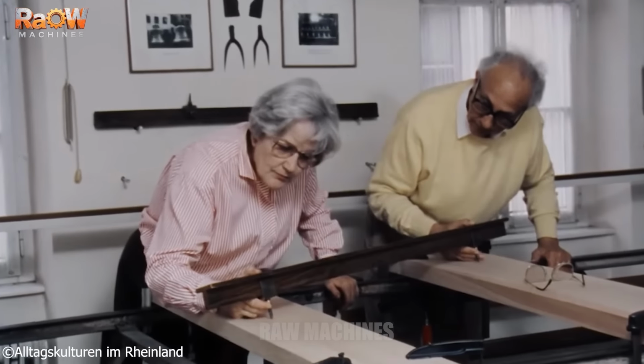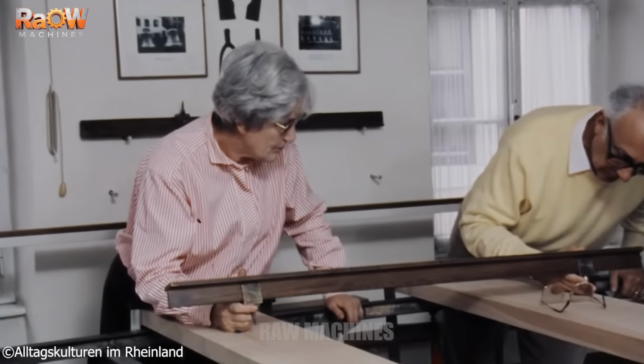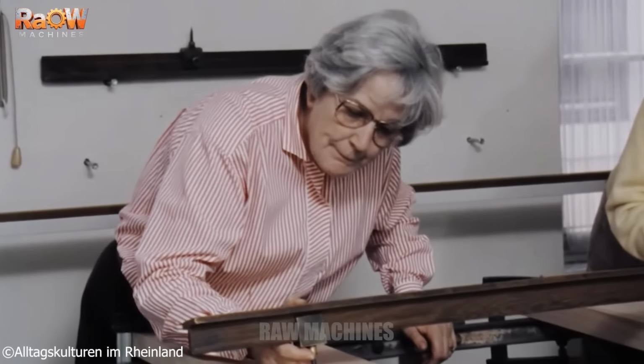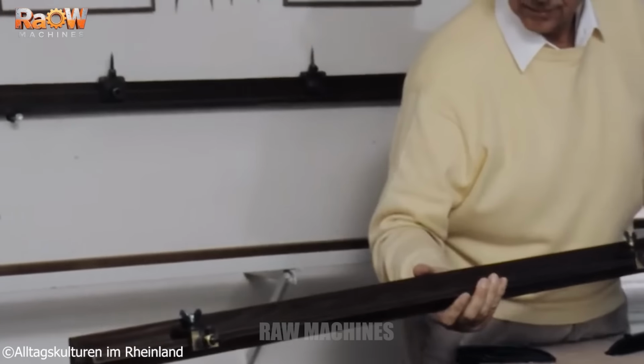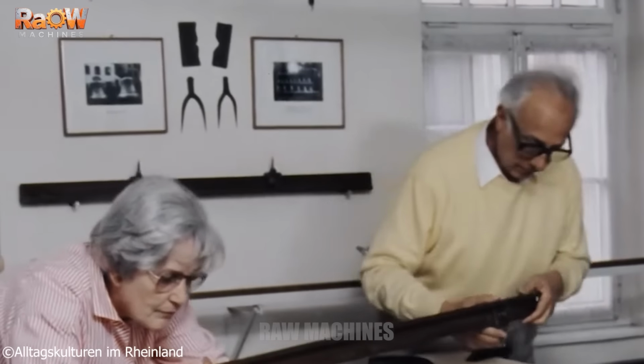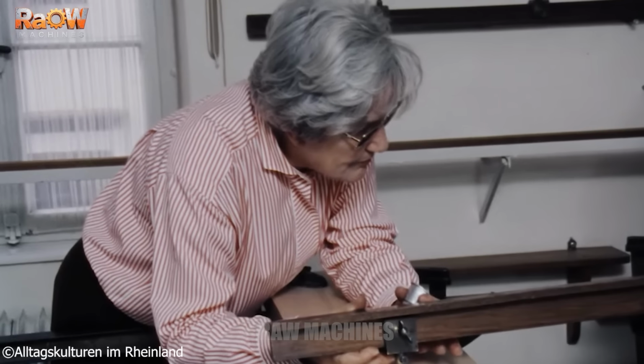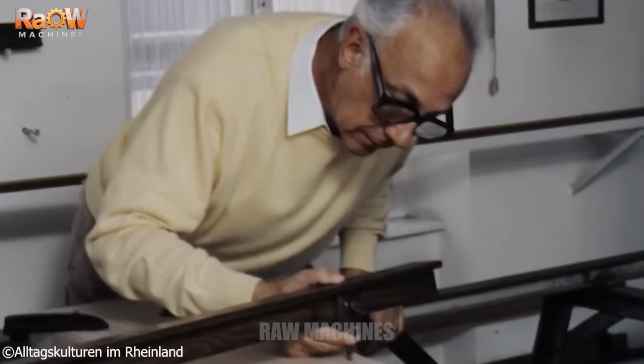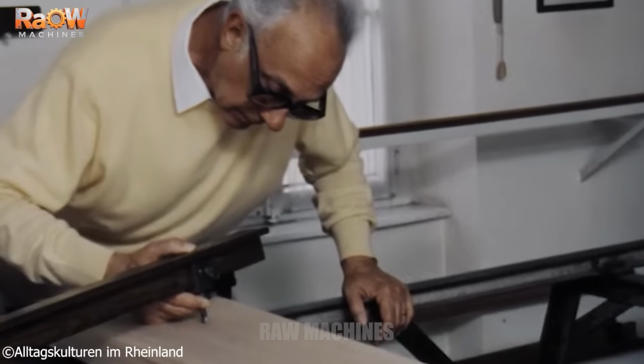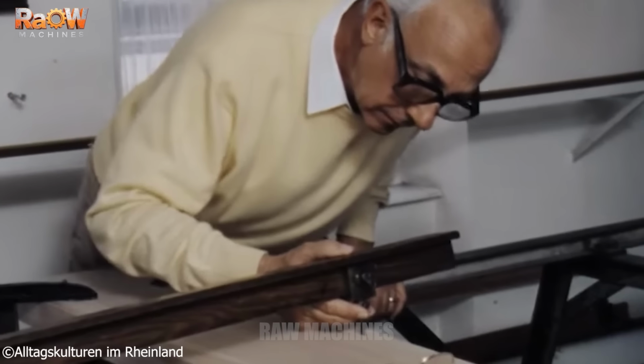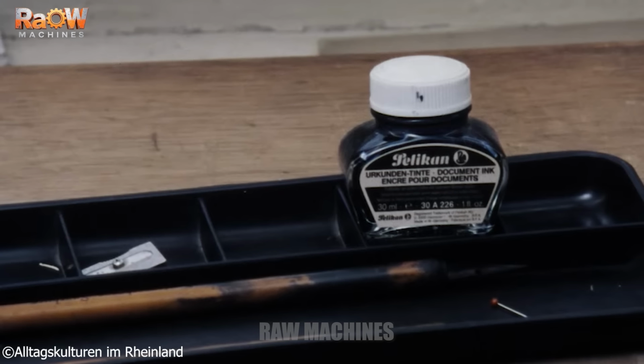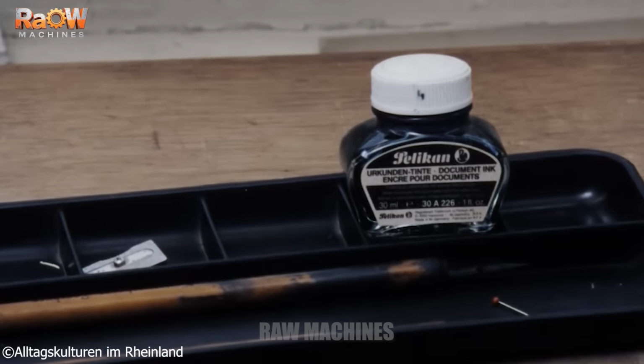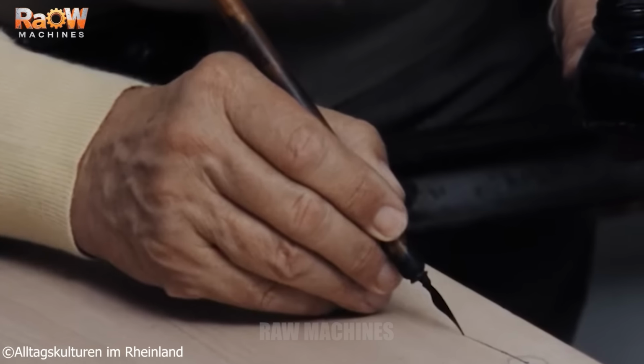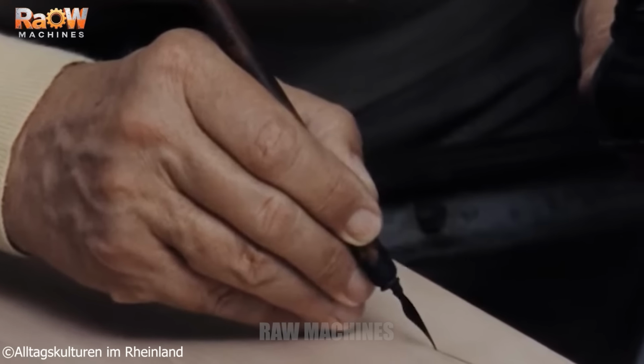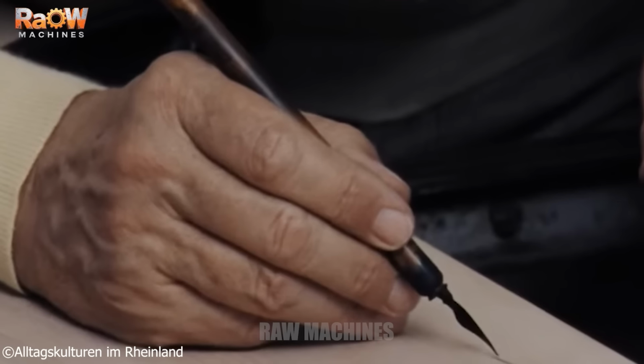Working together with Marian Mabalon, these coordinates are then transferred onto a second board to create the finished schablone. Two curves appear on it, representing the inner and outer surfaces of the bell wall. These lines are inked to ensure accuracy during use. The schablone also records the intended pitch and the name of the commissioning parish. Before being put into service, the board is carefully cut and shaped along the defined profile, making it ready for the subsequent stages of mold construction.